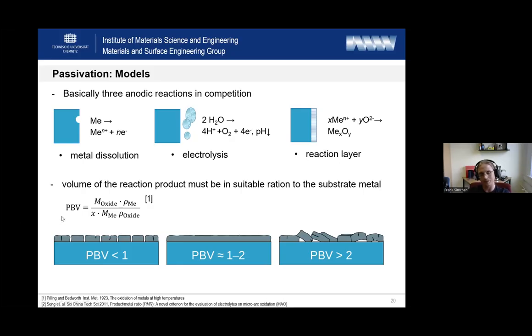So this relation was firstly scientifically described by 2 scientists, Pilling and Bedworth. They created a so-called Pilling-Bedworth ratio, which should be here in R, not in V, because in Germany it's Pilling-Bedworth-Verhältnis. And if the volume of the oxide and the volume of the metal is in an unsuitable range, below 1, you get your electrical isolating oxide, but you don't get a dense oxide layer. You get something where permanently appear cracks.